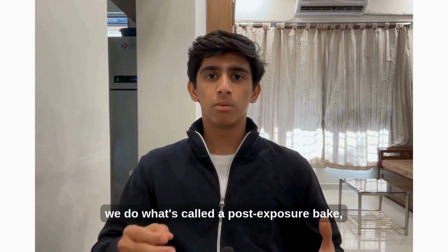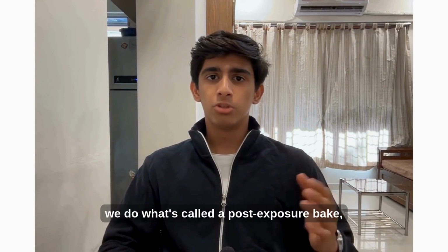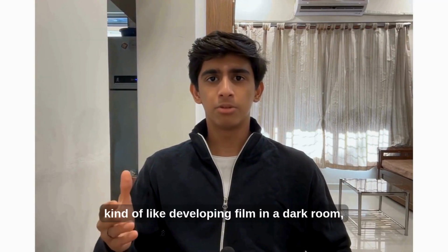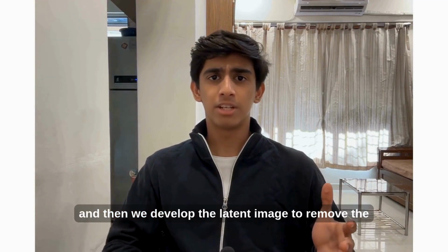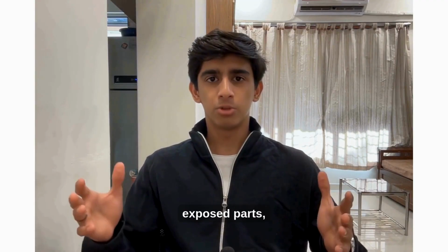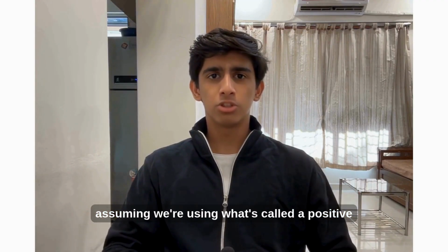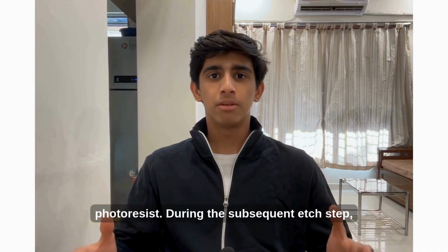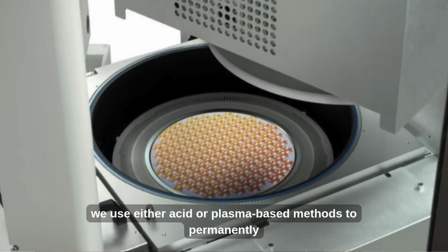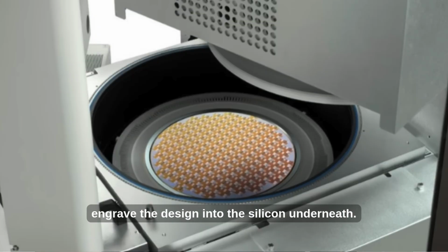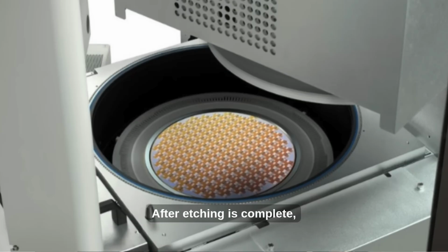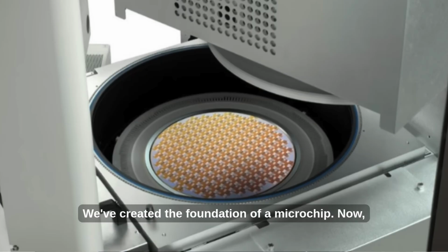After exposure, we do what's called a post-exposure bake, kind of like developing film in a dark room, and then we develop the latent image to remove the exposed parts, assuming we're using what's called a positive photoresist. During the subsequent etch step, we use either acid or plasma-based methods to permanently engrave the design into the silicon underneath. After etching is complete, we strip off the remaining resist and voila, we've created the foundation of a microchip.